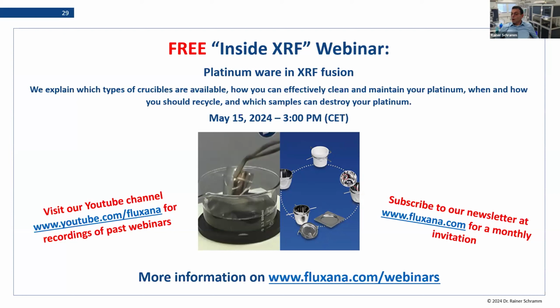Another question: what is the optimal quantity we should use for the right fusion? I would say you should always start with a middle flux, the 6634, what I mentioned, and then a ratio of 1 part sample, 8 parts flux, and then you start. If it cracks and it doesn't work, I would dilute first, and I would add perhaps some non-wetting agent, but do it always step by step, not at once, so that you get a feeling in what direction it will improve.